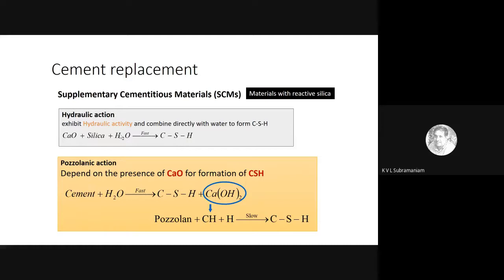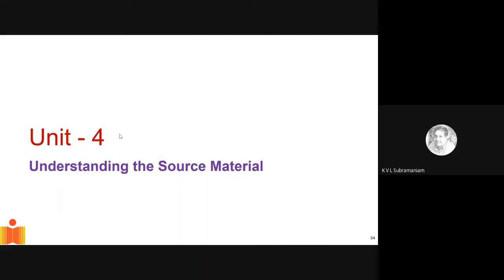And again, it is used as a replacement. It can also be used as a cement replacement. And the whole point is that the calcium hydroxide that is produced from the cement hydration is then used up by the silica that is coming from these materials to form additional calcium silicate hydrate. So that is the whole principle of this utilization.